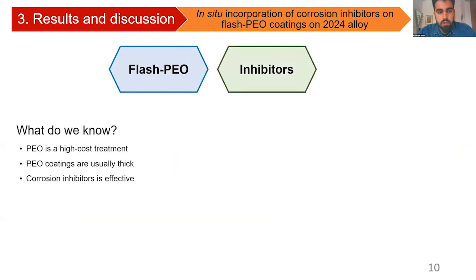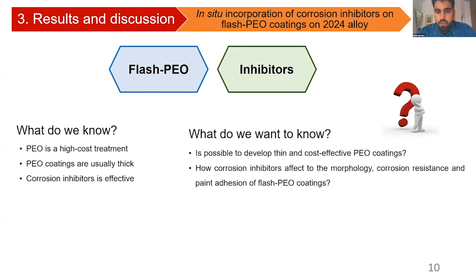So far, we know that PEO is a high-cost treatment, PEO coatings are usually thick, and corrosion inhibitors are an effective way to increase the corrosion performance. So we would like to know if it's possible to develop thin and cost-effective PEO coatings on 2024 aluminum alloy, and how corrosion inhibitors affect the morphology, corrosion behavior, and paint adhesion of these flash PEO coatings.